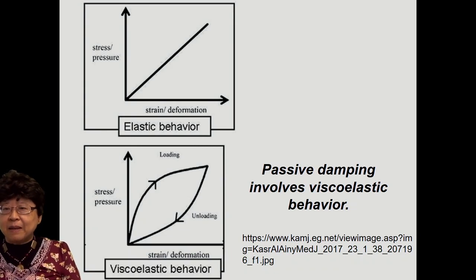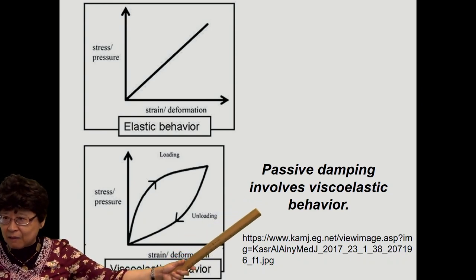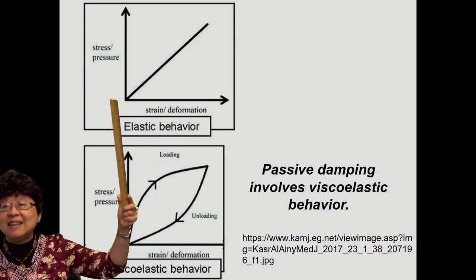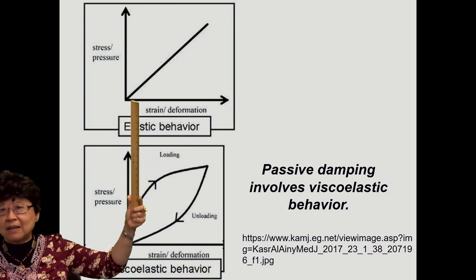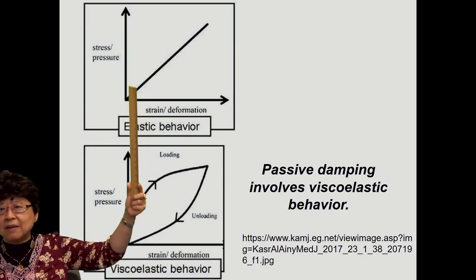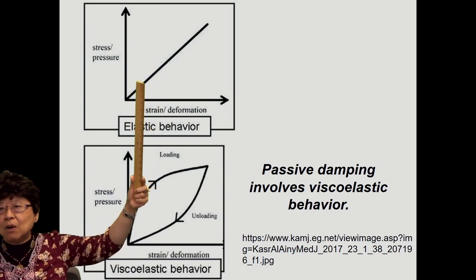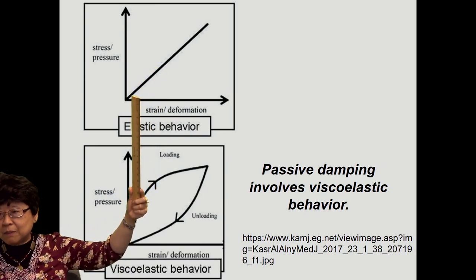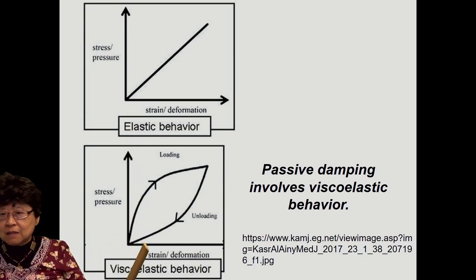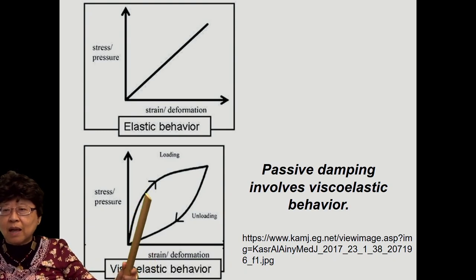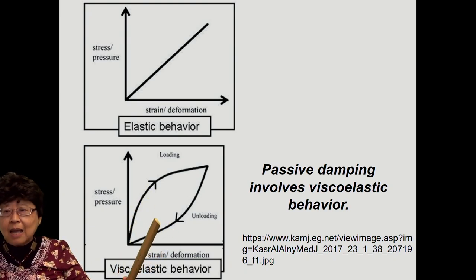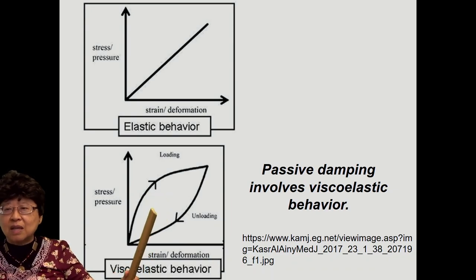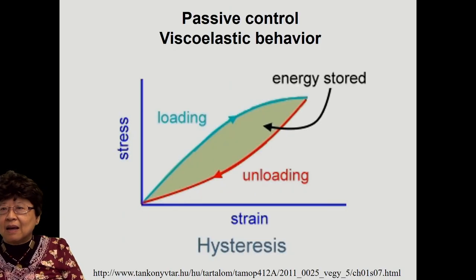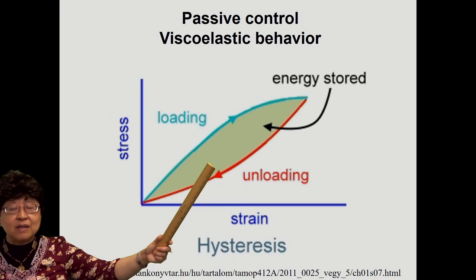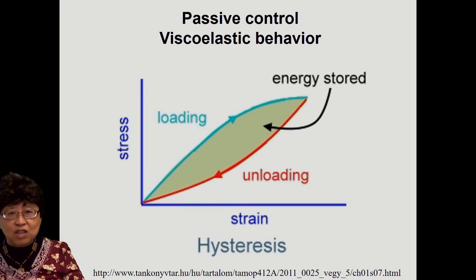Now, passive damping utilizes the viscoelastic behavior of materials. Up here is the elastic behavior, totally elastic, not viscoelastic, which means that the stress and the strain are linearly related, and the loading and unloading curves exactly overlap. There's no hysteresis. But in the viscoelastic behavior at the bottom, the loading and unloading curves don't overlap. As a result, there's hysteresis, and this results in energy dissipation. And this area of the hysteresis is actually related to how much energy is dissipated per unit volume per cycle.